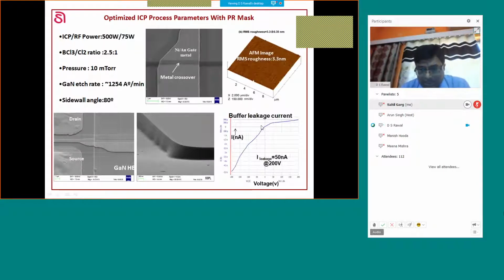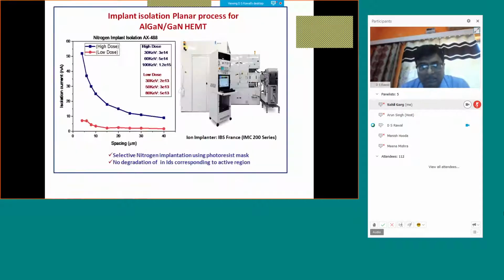This process is conventionally used for mesa isolation, but these days the preferred process is ion implantation because it gives you the flexibility of a planar process. This planar process is preferred for high frequency applications beyond X band or Ku band. So now we have developed this process also, in which we are damaging the unwanted area by nitrogen implantation so that there is no flow of current. You can see that we have two different implantation doses in which nitrogen is implanted in the unwanted regions where we don't want any electrical current to flow, and that is done using selective implantation through photoresist.